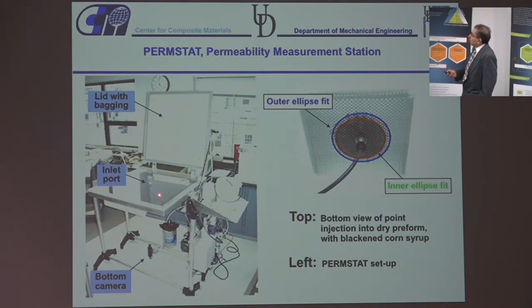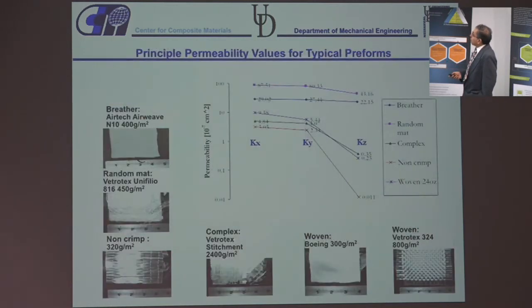We inject the resin from the bottom into the fabric, and we had a camera at the top and a camera at the bottom. By image analysis, we can match how the flow front is flowing at different time steps. From that, we were able to analytically calculate the permeabilities of various fabrics in the X direction, the Y direction, and the Z direction.